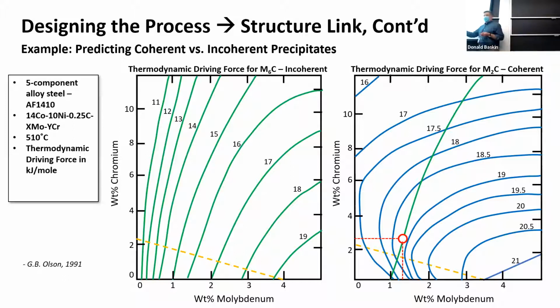You guys want to take a second to breathe that in? Okay. You guys got that? Not seeing many shaking heads, huh? Okay, try it again. So there's coherent precipitates and incoherent precipitates. Coherent ones means that the atomic planes line up. Incoherent means that they don't. It's almost like a little ball sticking in there that isn't really attached to all the stuff around it. Okay? The M6C carbides are incoherent. There's also some corrosion things there that I think happen at a really small level. The M2C carbides are coherent. In order to get preferentially one over the other, you pick the one that has the higher driving force. And then you want to maximize that driving force in order to try to form this finest dispersion of these precipitates.